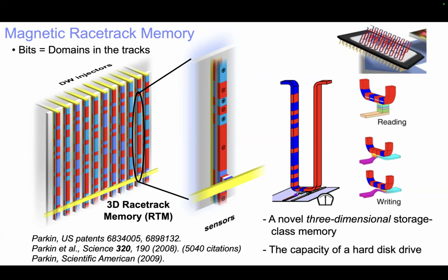So this is very different from any other memory device in the sense that the information, the data, is physically moved, but without moving any atoms, only by rotating the magnetic moments. And this is crucially important. Typically, memory devices involving the motion of atoms, such as ferroelectric memories and phase change memories, have failure mechanisms that prevent their widespread use. So racetrack would then require billions of these racetracks, each one storing 100 domain walls or more.